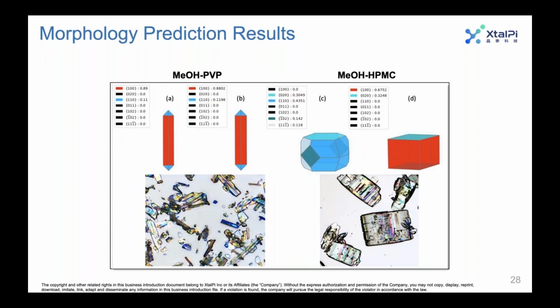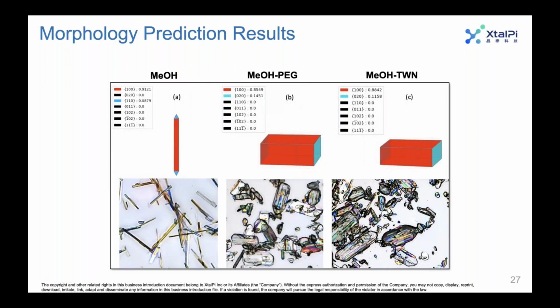Here we have a few more examples from MEOH. Specifically, this experiment was MEOH with PVP. Interestingly, PVP does seem to change the morphology from pure MEOH, where we get extreme needles, but we don't see the same type of change that we see with some of the other polymers. We still get a fairly needle-like crystal, and the simulations are able to capture that. So what we're seeing is that the 110 face doesn't disappear when the PVP is added. Therefore, you don't shift away completely from a needle-like morphology.